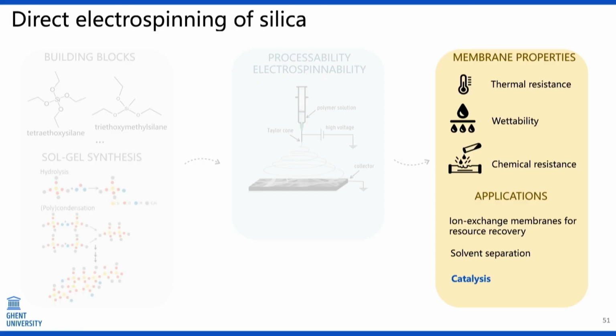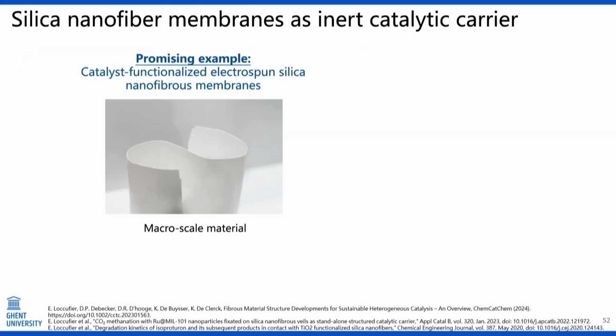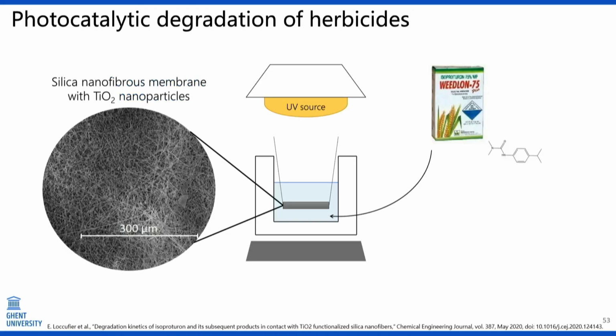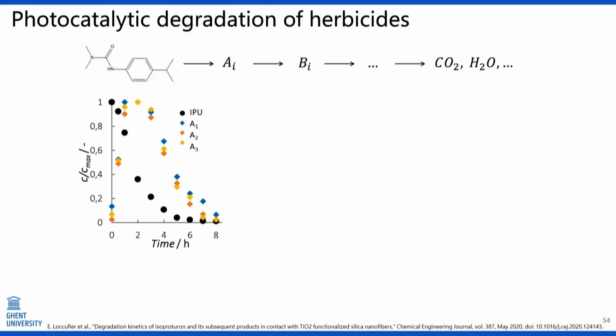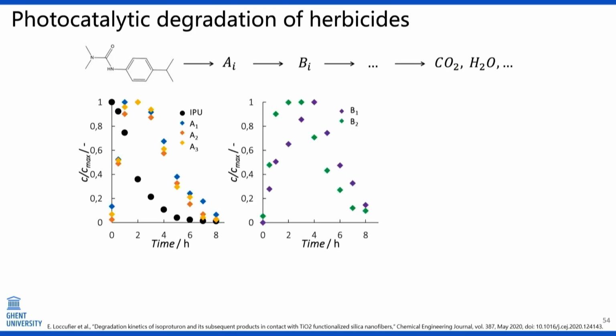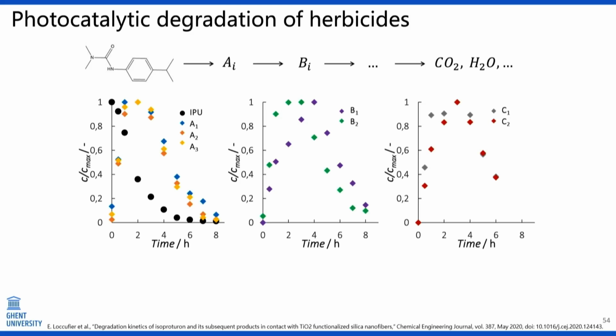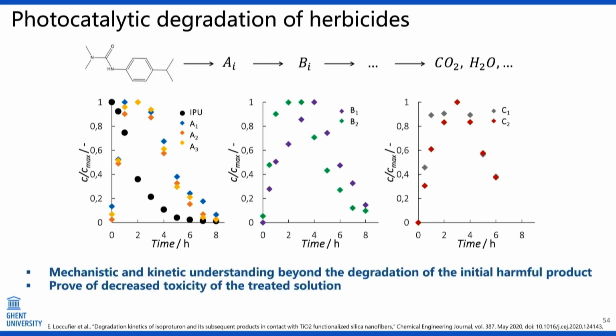And then the last applications of this silica are different catalysis processes in which we used the silica as an inert carrier for different catalytic nanoparticles. And again, the advantage of the silica is, for instance, the very high thermal stability, which is sometimes needed at very high temperatures for these catalysis processes. An illustration here is with titanium dioxide nanoparticles, which we used for degradation of herbicides. And we showed that it did not only decompose the herbicide into the first degradation component, but also the second and the third and so on components were nicely degraded, allowing for proving that we had indeed a degradation into a full unharmful product, because some of these side products are also harmful.